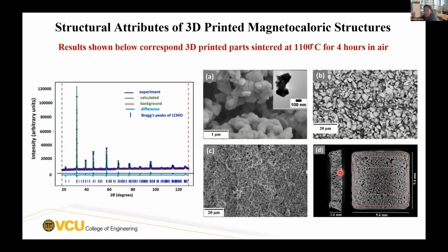But his parts are porous. You can see here the cross section of a computed tomography of a sample made by sintering at 1100 degrees Celsius for 4 hours, and it has around 20% porosity.